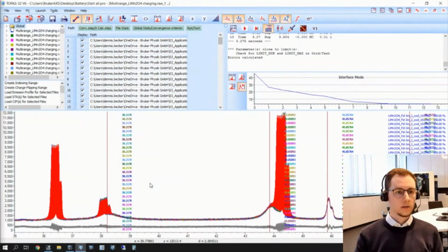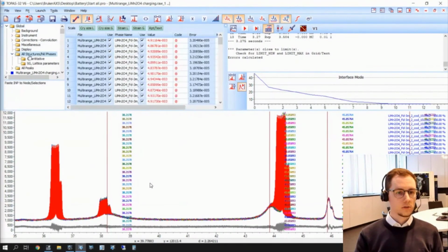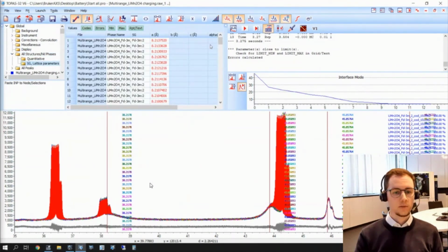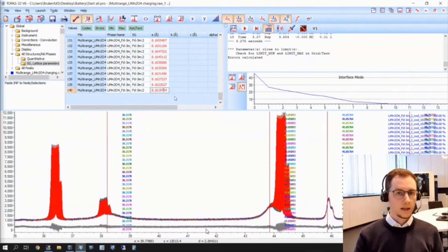Zooming out again. And I can, of course, also get the information about the lattice parameter, for example. So we started here in the first range with a lattice parameter of 8.21 angstrom, and then the lattice parameter decreased down to 8.16 angstrom. I can copy this now, put it into Excel or into any other program and visualize it. I can calculate from the cell volume, maybe the lithium content. I can visualize all the things I need now. So TOPAS allows you to fit all of this multi-range data you produce with the battery cell.